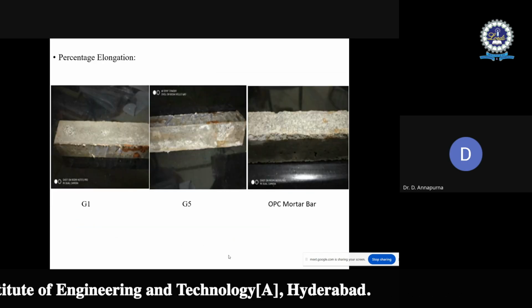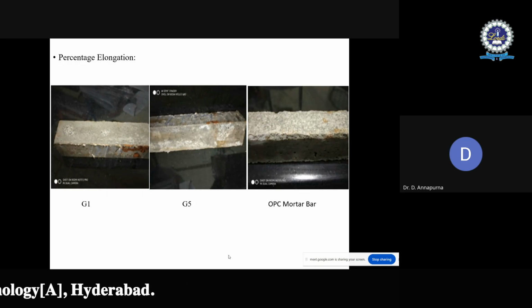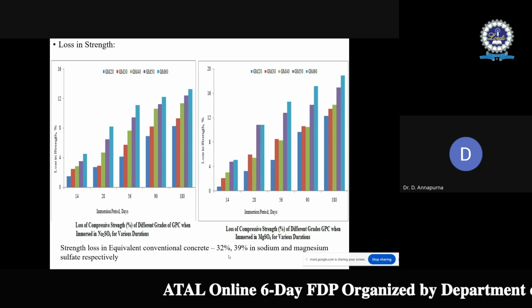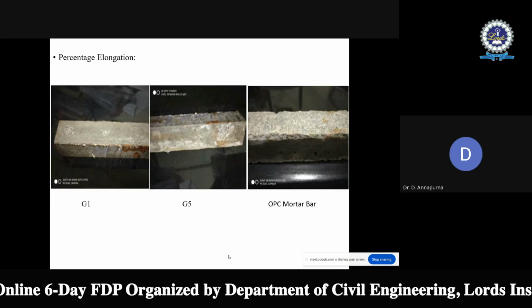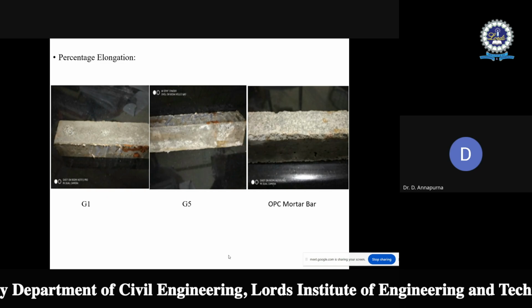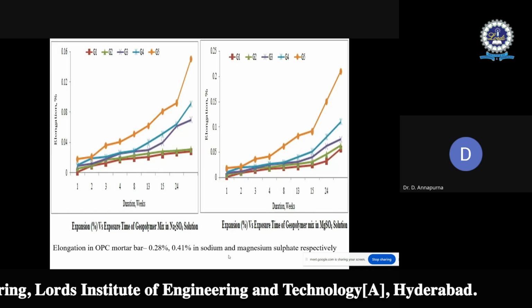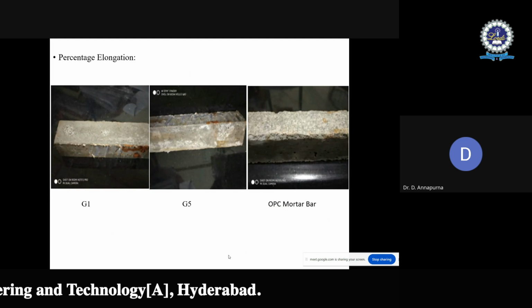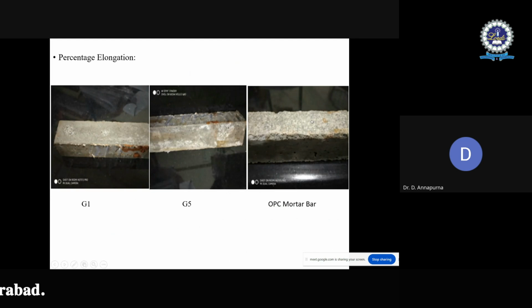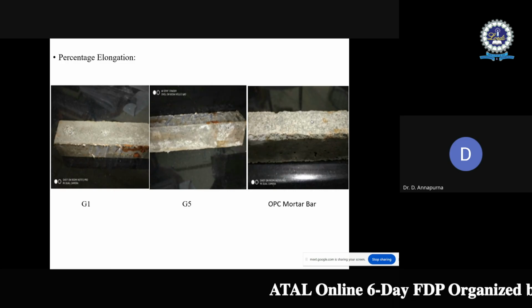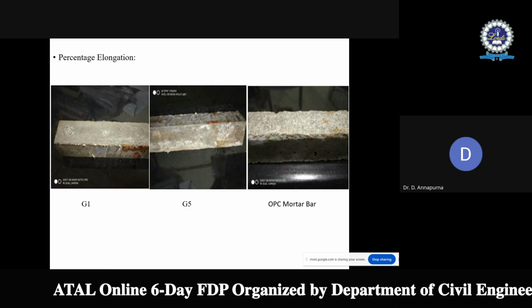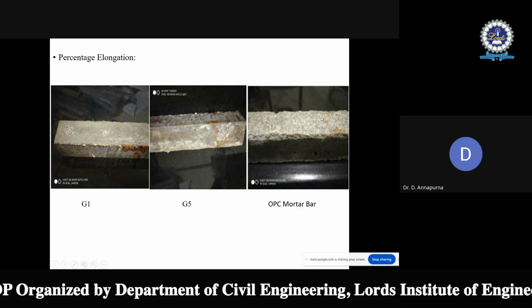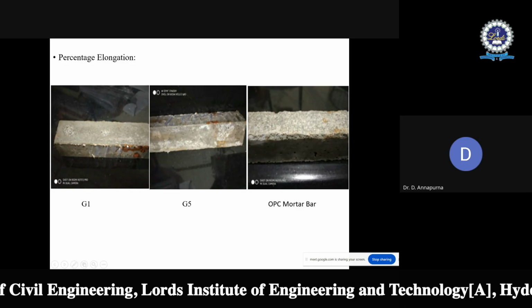The next one will be the sulfate expansion test. Along with the percentage loss in strength and weight loss, the sulfate expansion test is also conducted using the mortar bars. The result depicts a similar kind of behavior. If you look at the OPC mortar bar, it is showing a large amount of white patches. Normally, whenever sulfate is attacking the concrete, the physical observation will be the formation of white patches. The white patch is nothing but ettringite, right? Ettringite formation is very high compared to the geopolymer products.